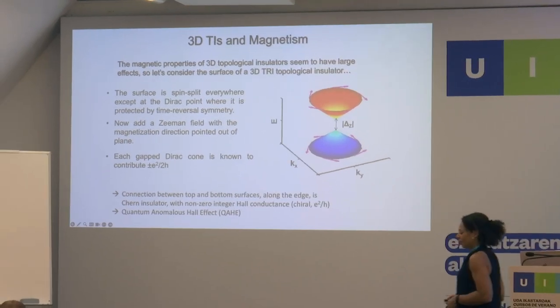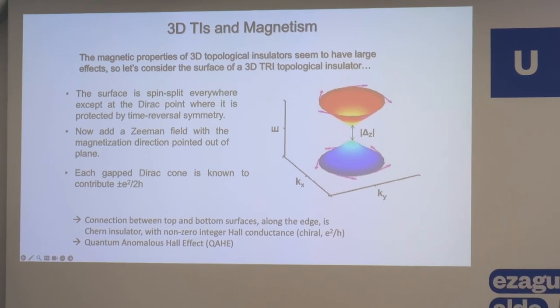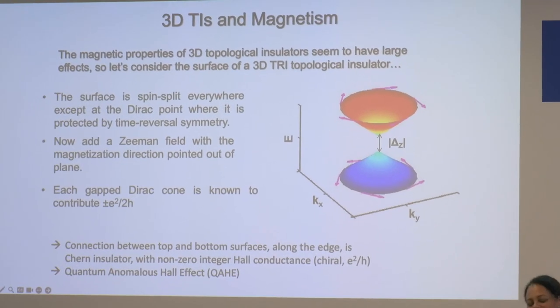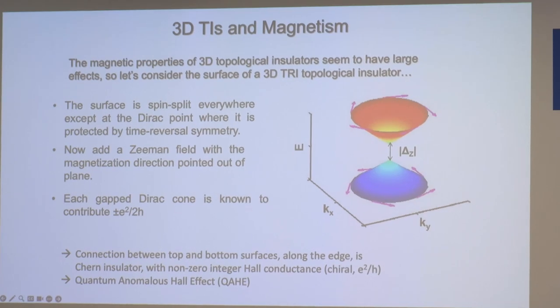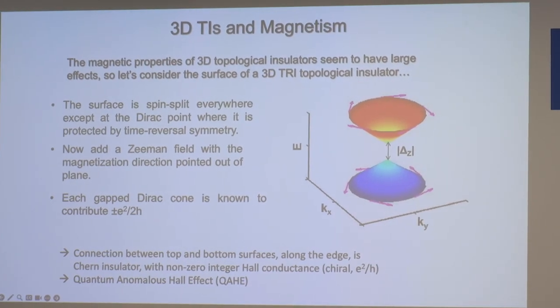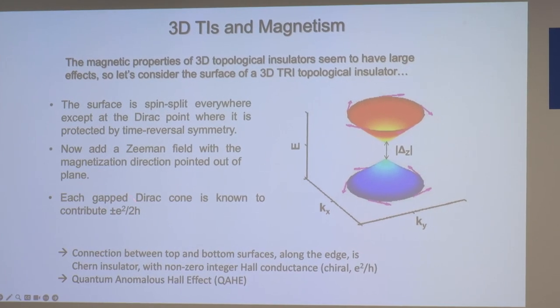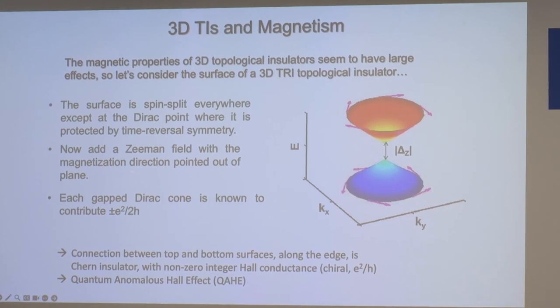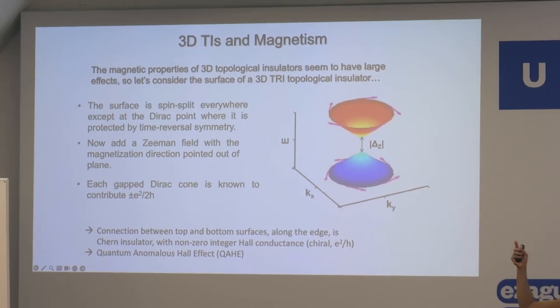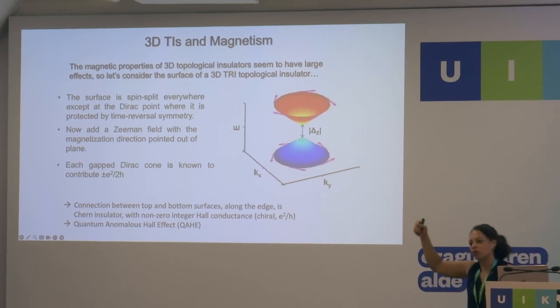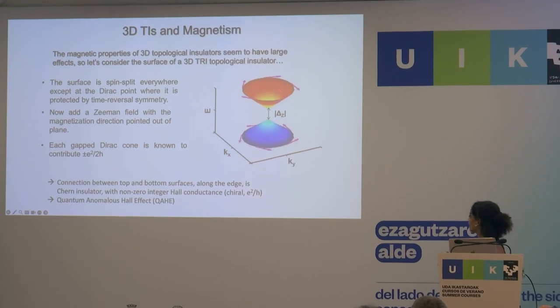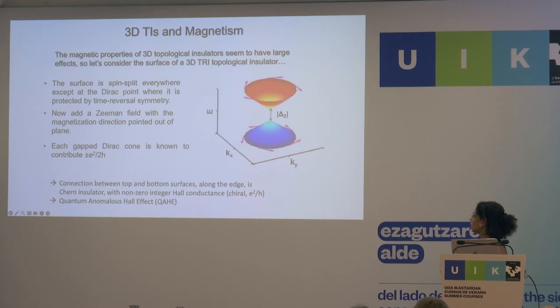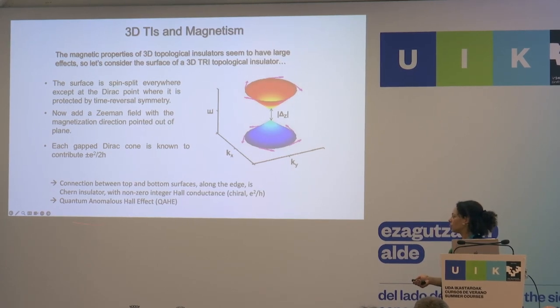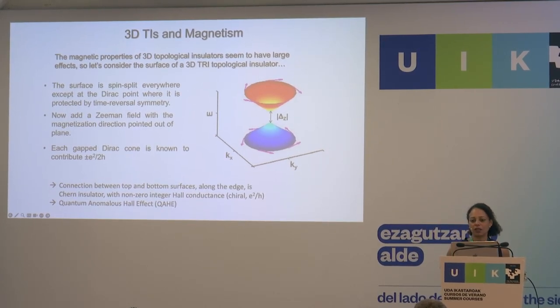And you've heard a lot of theory. As an experimentalist, I like to give very hand-wavy points of view, so sorry if this is wrong, but I do like to think about if you're connecting surface states with opposite spin contributions, you have to somehow connect them along an edge, right? If you want to have current go continuously from one to the other across this gap, there has to be an edge state in the middle, and that is your chiral e squared over h Hall conductance that's expected in this case, which is predicted for the quantum anomalous Hall effect.